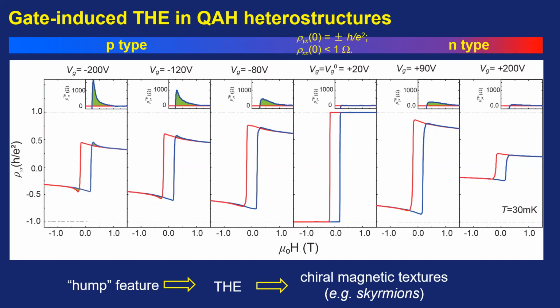They followed up with, could the same effect be seen with 2D material regimes? Yes, if the 2D material has the quantum spin Hall effect or topological property, in principle, you can also realize the quantum anomalous Hall effect. There are 2 channels in the quantum spin Hall effect. If you can kill one channel by ferromagnetic doping, in principle, you will realize the quantum anomalous Hall. For example, in monolayer tungsten telluride, the quantum spin Hall effect has been observed. So if you can introduce some ferromagnetic order in tungsten telluride, which kills one channel, in principle, that should give the quantum anomalous Hall effect.